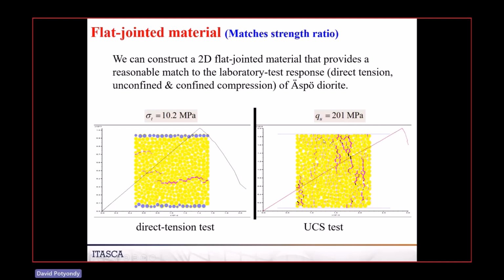And if we look, notice what you've got is the thickness of these are the cracks. These are broken elements. Remember, the flat joint in this case has 4 elements. Each flat joint interface has 4 elements, each of which can independently break. And so each of those little elements is drawn here. So right up here, there's only one of the 4 that's broken, so it's a very short break. And the thickness of these lines is proportional to the current gap, how much open that thing is. And so you can see at the peak, we've gotten this big amount of opening going on here, and we have quite a bit of distributed damage before that.